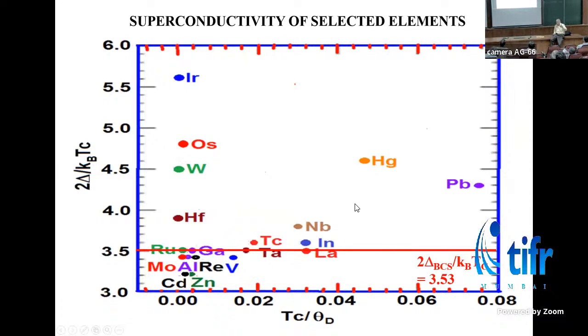The delta was a prediction of BCS. And you see even the elements, they don't fall into the BCS shape. It's not surprising, basically because they have very complicated structures, Fermi surfaces. You cannot use simple BCS to expect that everything should fall on the line. So this is an interesting thing, like things like iridium, it's an extremely strong coupling superconductor.